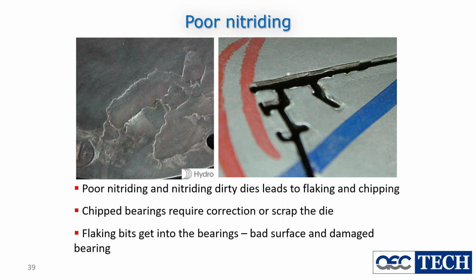I was working for a while with Hewlett Hydro down in South Africa, and we were working with their nitriding. We always like people to wear gloves when they're loading the dies. And one guy decided, for whatever reason, not to wear gloves this day and left a greasy fingerprint on the surface of the die. You would think that would have no consequences whatsoever. In fact, it didn't harm the die in any way. It's just that there were no nitrogen atoms formed where the grease of his fingerprint was on the surface of the die. It looked no different at all when it came out of nitriding.